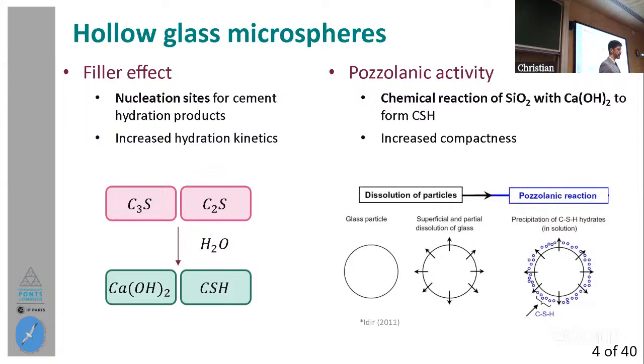This is at short curing time, but then at long curing time, we can also have a pozzolanic activity. This is known as a chemical reaction between the silica, in this case of the spheres, and the calcium hydroxide from cement hydration to form secondary CSH. This is also a chemical reaction very well known for increasing the compactness of the cement matrix, which a priori is a good thing.